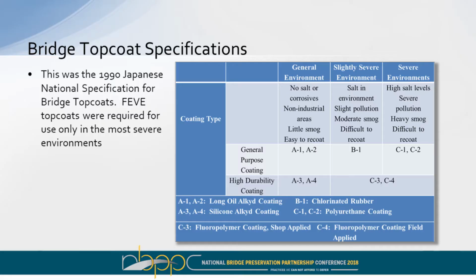offer against corrosion. There are a number of bridge top coat specifications with this. These products have been used in Japan for close to 30 years now, maybe even 35 years. And the standard you're looking at here is the 1990 specification for bridge top coats. And what you can see is they define different environments. They define the environment, and then they specify the types of coatings that can go in there. And at the time this was done, they were still using alkyds, chlorinated rubbers, polyurethanes, silicone alkyds, and you can see then that they recommend only for the worst environments the fluoropolymer coating system.